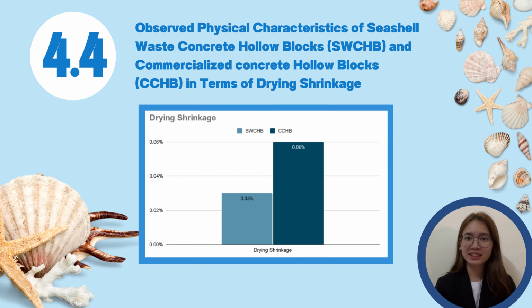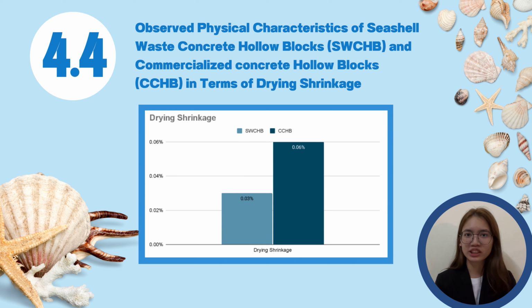This graph represents the data of the observed physical characteristics of the seashell waste concrete hollow blocks and the commercialized concrete hollow blocks in terms of their respective drying shrinkage. The diminution in volume or the size of the hollow blocks that happens during the drying process is referred to as the drying shrinkage. As shown in the graph, the drying shrinkage of the seashell waste concrete hollow blocks is 0.03%. On the other hand, the drying shrinkage of the commercial concrete hollow block is 0.06%, which is higher.